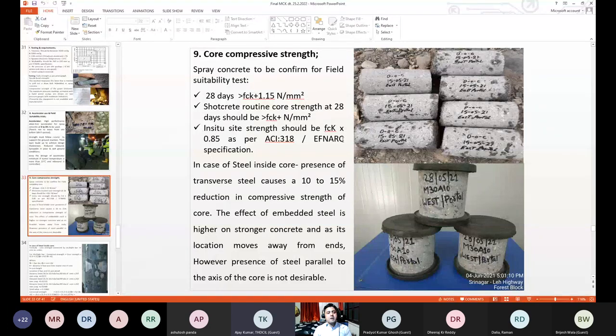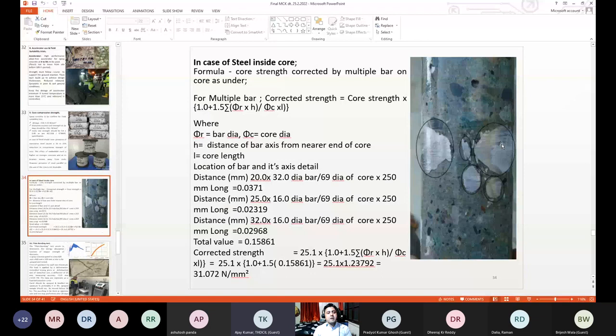This is the sample of specimen which you generally take from the site, and if there is steel in the concrete sample or core sample, you can go with the same corrected strength formula. You have to identify the length and the diameter of the steel bar, how much length and how much diameter exactly is in the core, and you have to calculate accordingly.